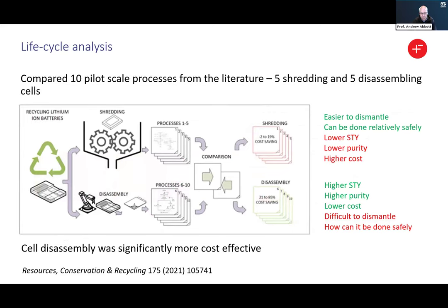So we carried out a life cycle analysis, whether it was better to shred or to separate samples. We carried out data from our own processes and those from the literature. And what we found was that you could get a significant cost saving, maybe even up to 80%, as opposed to mining those materials by separating rather than shredding those materials. So the problem is at the moment, as we've said, battery designs are not conducive to be able to separate. And so probably for the next 10 to 15 years, shredding is probably one of the main ways forward, although there are some exceptions out there that I'll discuss in a minute, where people are already disassembling cells.